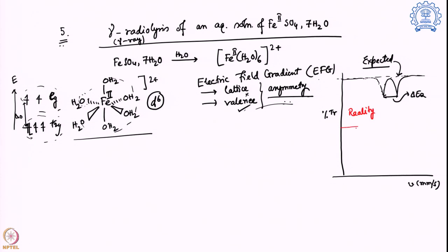What we see is the following. Over here, if I take the average of these two lines, that is going to give me the delta value, and this difference is the delta EQ. This is in reality. Whereas the average of the expected one is almost at the same position. So the delta value or isomer shift is almost at the same position, but this quadrupolar splitting is much larger in the case of the reality compared to the expected.